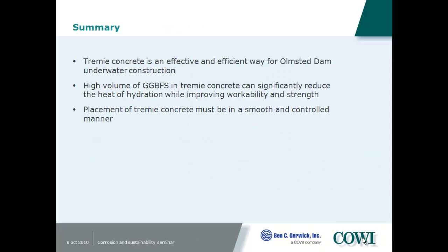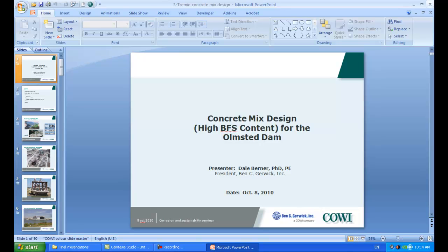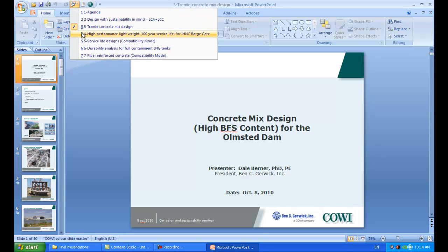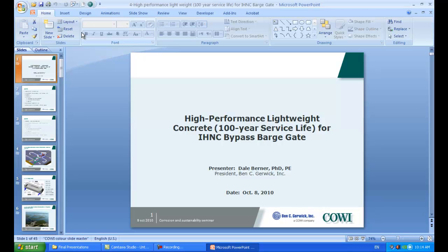Okay, so Tremie concrete is an effective, efficient way for the Olmsted Dam to be built underwater. We've had high volumes of granulated blast furnace slag to reduce the heat and improve the workability. And as I said, it's been demonstrated to be quite effective in practice, due to the rate of funding. They're not building it as fast as I might have thought would be optimal, so they only do so many shells a year, and then they start over again when the funding stream starts. So that's why there aren't more shells installed quite yet.